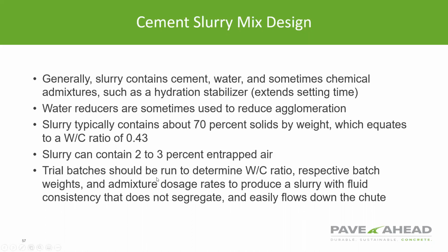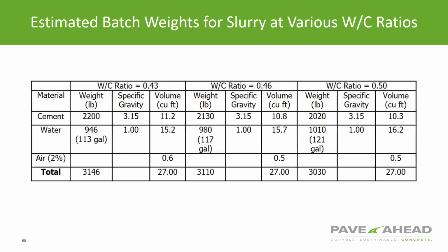And then trial batches can be run to determine the best water cement ratio with respect to the materials that a given producer has. We put together these charts really for a ready mix producer to provide a starting point, and this would probably be your preferred mix design, everything else being equal, so that you can get the most cement material out to the job site in a ready mix truck.